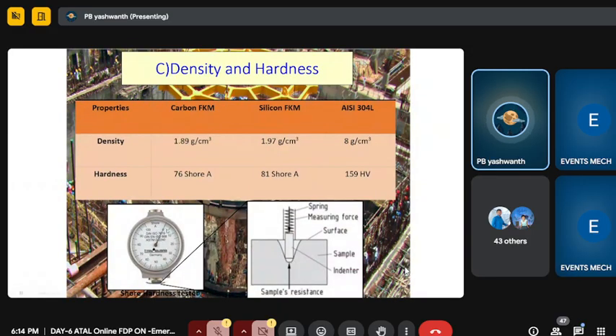Finding hardness using Rockwell and Brinell, we are all aware. Rubber hardness we are not aware of. So I just wanted to show this instrument that we use for finding the hardness of a rubber. The main mechanism here is the needle. It is almost like a pricking glucometer. One needle comes inside, pierces and goes back, giving a proportional value of the hardness. If this needle goes much deeper, you can understand the rubber is very soft. If the rubber is very hard, the needle travel will be much lesser. That is controlled by the spring. This is a Bareiss German make rubber hardness tester. I just wanted to show how hardness testing happens in rubber.